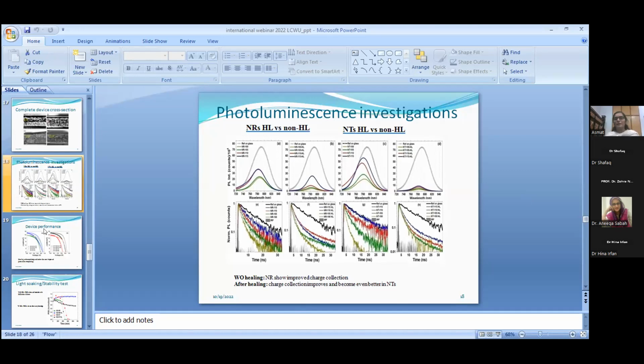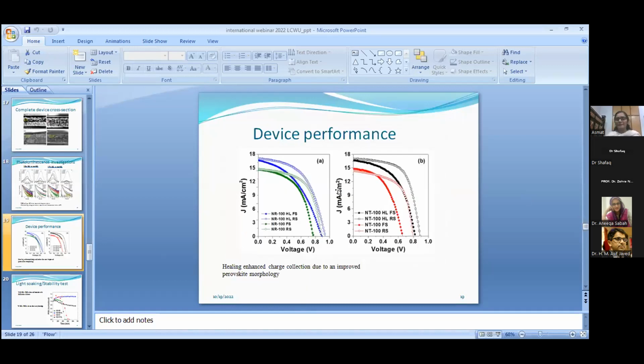Now we have the device performance of our lot of devices. Here we can see the nanorods, and here we can see the nanotubes, without healing and with healing. We can see that this is without healing and this is with healing. So there is a difference in the device performance of the nanorods, but the trend is much clearer in the nanotubes.